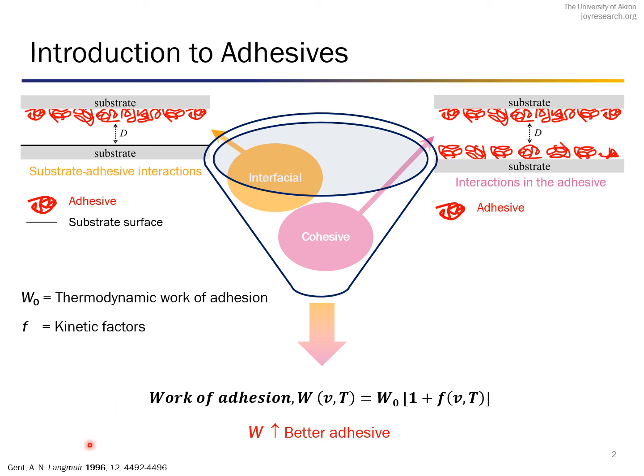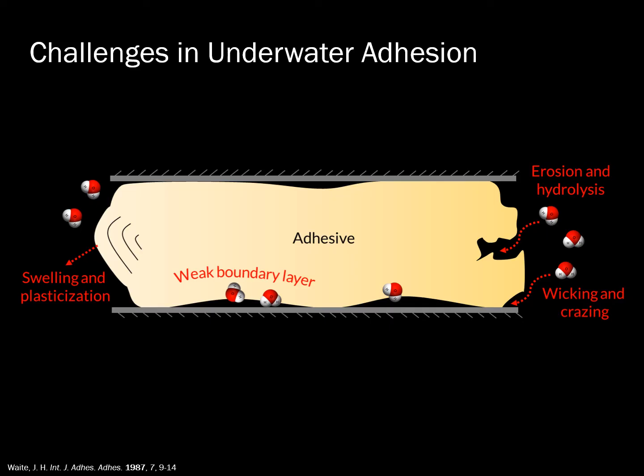Alan Gent from University of Akron derived this equation in 1996, and people have used this concept to create several varieties of adhesives. But all those adhesives fail to stick in underwater conditions because water can deteriorate the adhesion through four major mechanisms. First, the swelling and plasticization, which will kill the adhesive's cohesive strength. Second, the weak boundary layer, which kills the interaction between the polymer and substrate. Then wicking and crazing, and erosion and hydrolysis, are two other mechanisms through which water can act as a barrier for adhesion. Hence, the adhesion underwater is extremely different from the dry adhesion.